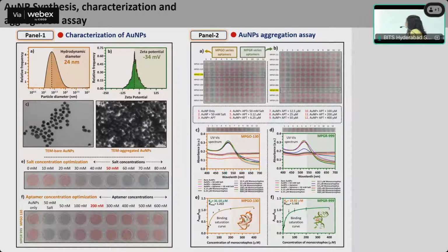And after aggregation, you can see the TEM image clearly showed that the particles are aggregated. Later, the salt concentration was optimized at 50 millimolar, and aptamer concentration was optimized at 200 nanomolar. With this, all the aptamers were studied in case of GO and GRNP SELEX, where we observed that MPGO-130 and MPGR-999 gave us very promising results, and further analysis was carried out to understand their binding affinity. Because it's very important to understand whether aptamers are binding with high affinity with the target or not. So in case of MPGO-130, the KD value was around 31 micromolar, and in case of NPGR, it was 19.92 micromolar.